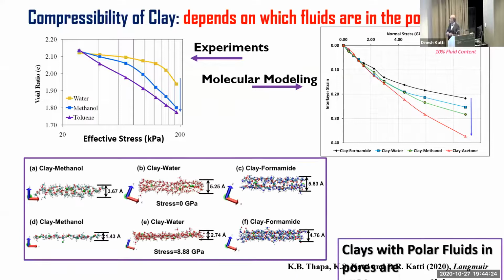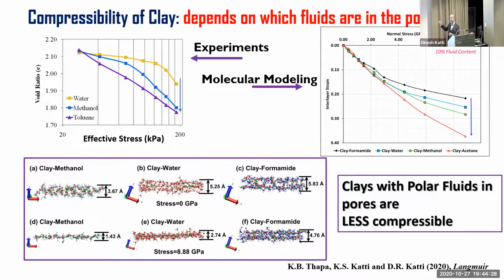Now we see the same type of thing happen with compressibility of the clay, the compression of the clay. And we find that clays, depending upon the nature of the fluid in the pores, the clays compress more or they would compress less. And again, that has to do with the molecular interactions between the clays and the fluids. So basically what we have found again here is clay with polar fluids, that is the fluids which interact the most with clays, are less compressible. The clays are less compressible. But if you replace the fluids with low polar fluids which interact less with the clays, you have more compression. So that's another engineering property. An important engineering property in addition to the flow properties is the compressibility. And we see exactly the same thing happening for the strength properties.